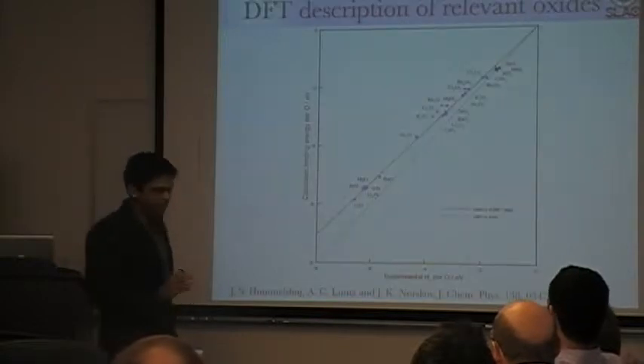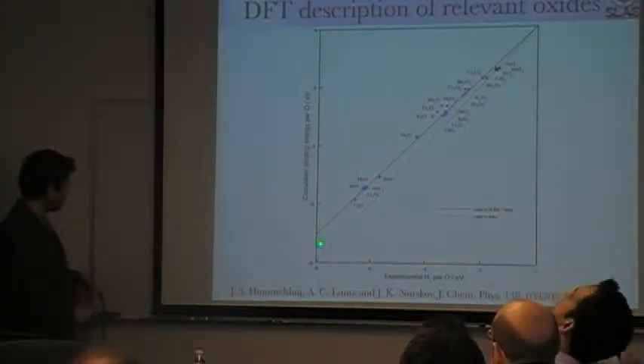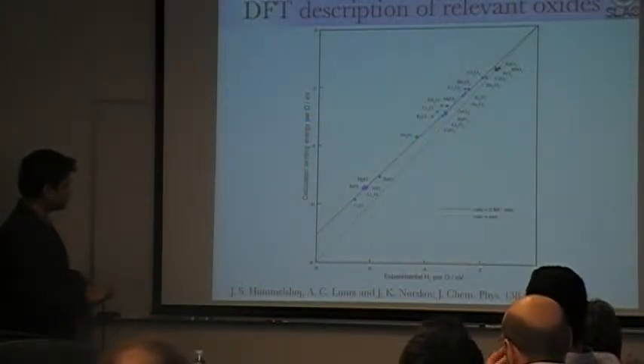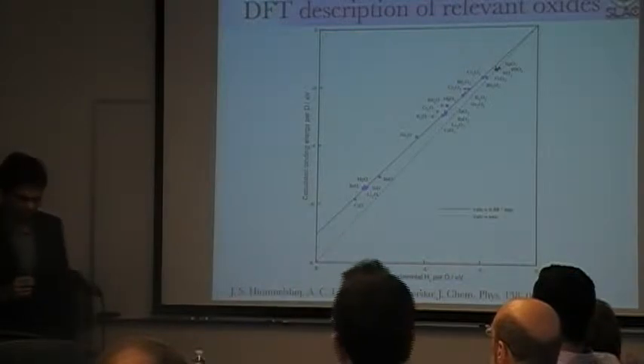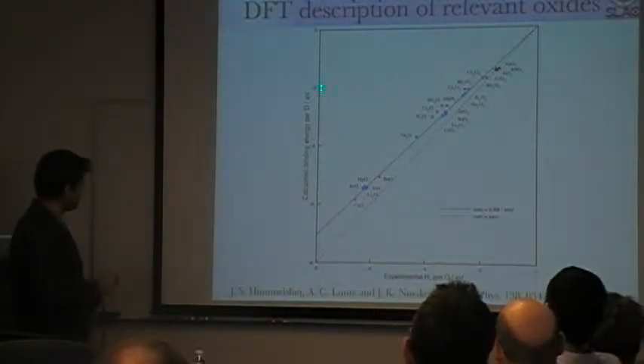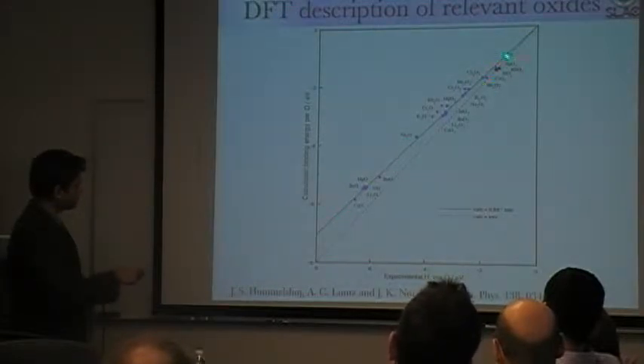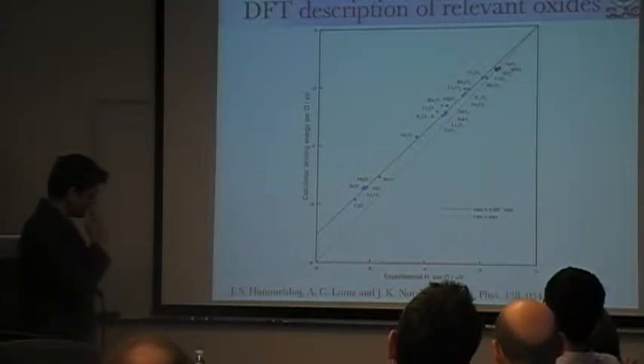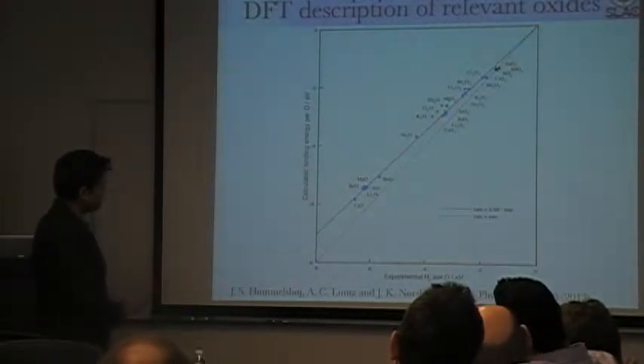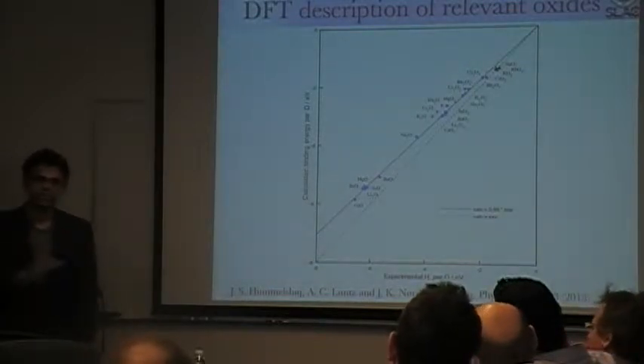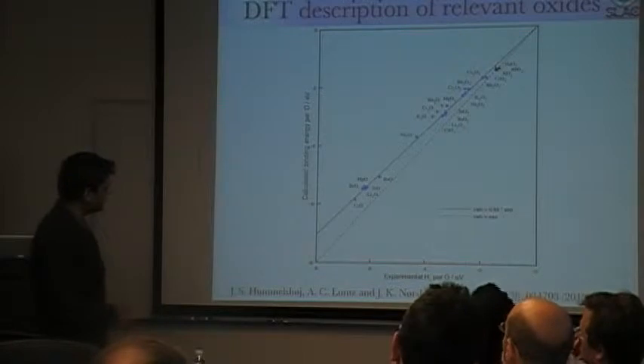This is my one slight validation of the methodology. This is a plot of the binding energy per oxygen for a whole host of oxides. Traditional density functional theory based methods are notorious for describing oxides poorly. But for this class of oxides, we show that the calculated heat of formation versus the experimental heat of formation has reasonable predictability. Shown here are superoxides, peroxides, and oxides. Although there's not a one-to-one correspondence, we can at least get trends between materials reasonably well. You can think of all the analysis presented as accurate to about 10% quantitatively.